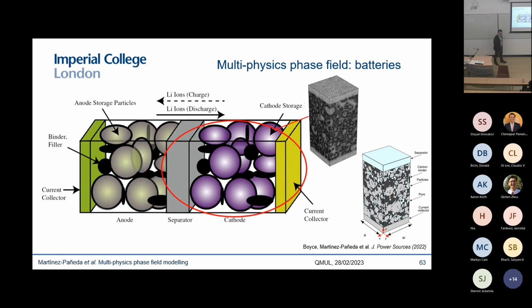But we have also taken this one step further. This is work together with Alan Boyce and Paul Shearing at UCL. We have decided to go one step further and model the entire electrode. You can see here that this also builds on the fantastic imaging capabilities that they have there at UCL. So we're able to characterize the entire electrode, and therefore we can not only model electrode particles, but we can also model other phases like pores and carbon binders, and we can see the role that these multiple phases play.